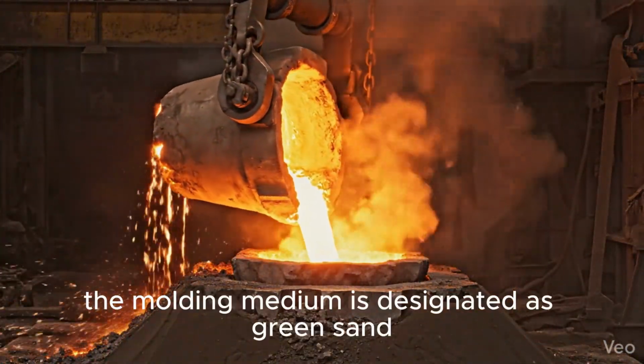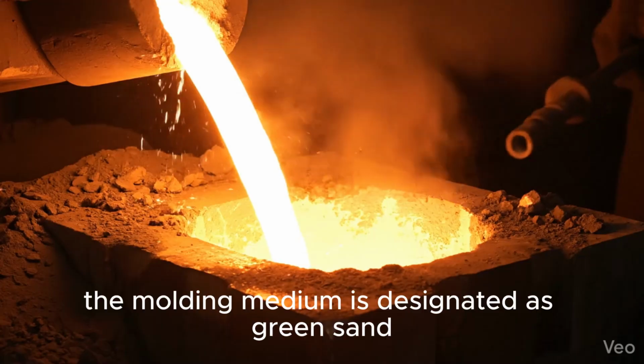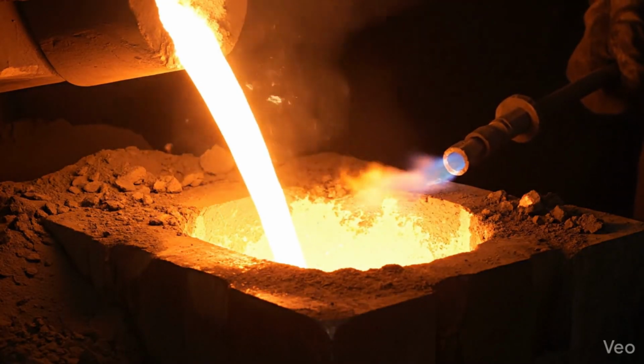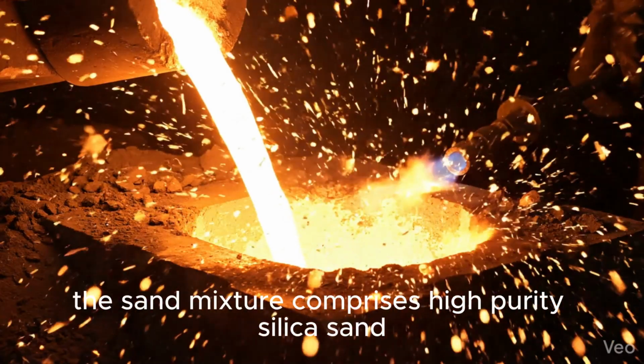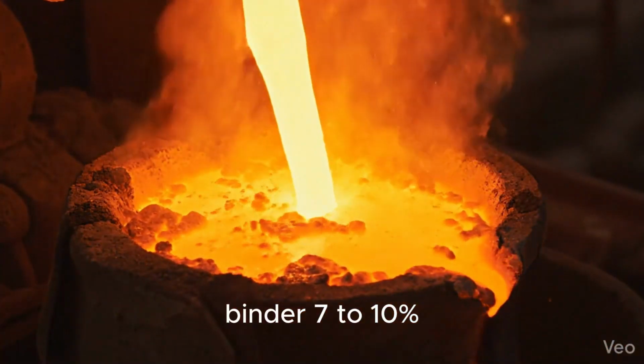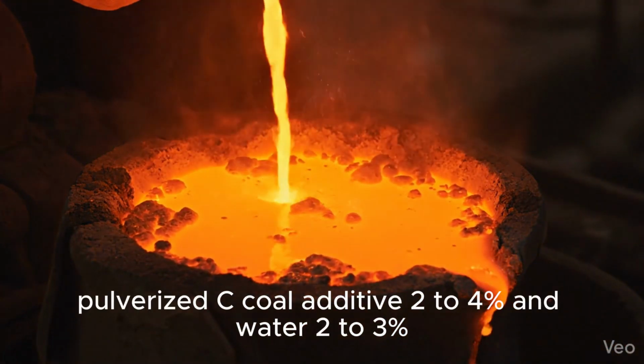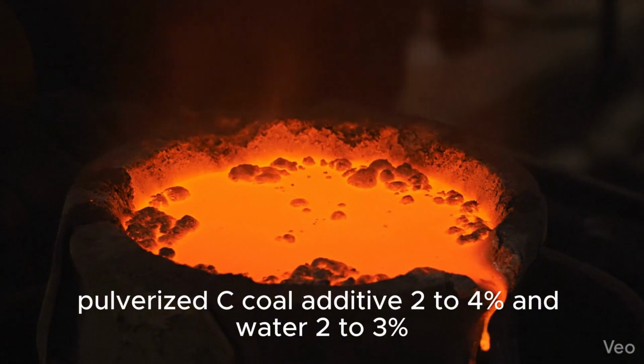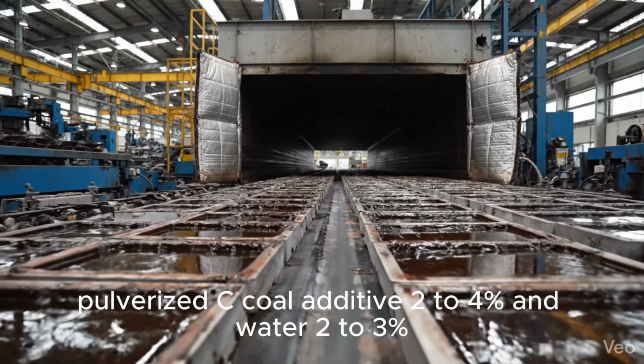The molding medium is designated as green sand due to its moisture content. The sand mixture comprises high-purity silica sand, 85 to 89%, sodium bentonite clay binder, 7 to 10%, pulverized sea coal additive, 2 to 4%, and water, 2 to 3%.